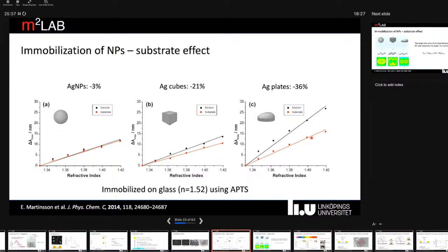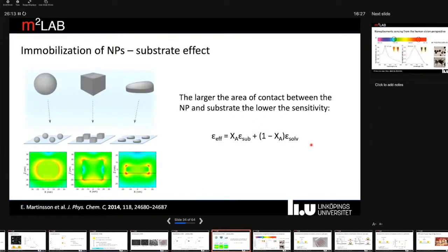As we can see in this data here, we have spherical silver nanoparticles. And if we immobilize them on a glass substrate, there is essentially not much of a difference in sensitivity, whereas if we go for cubes or plates, also silver-based, we see a quite dramatic decrease in sensitivity. And these particles were originally more sensitive than the spheres here, but due to this effect, this difference is decreasing quite a lot. And this is due to the high refractive index of the substrate, resulting in some of the electric field being distributed into the material instead of probing the surrounding medium. And the larger the contact area between the particle and the substrate, the larger is this substrate effect. So we should try to keep this at a minimum, or, if this is critical, use low refractive index substrates.